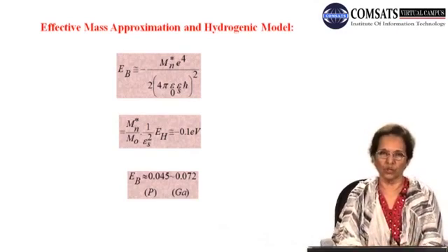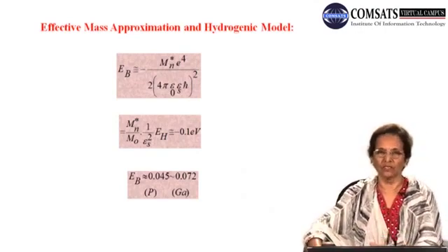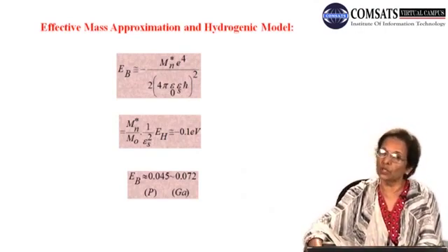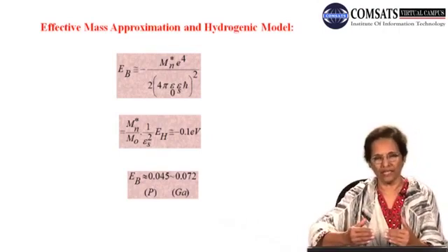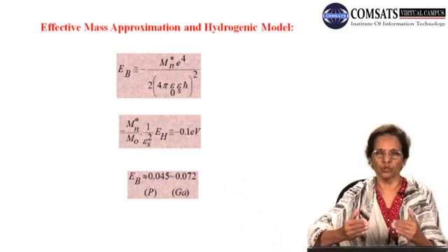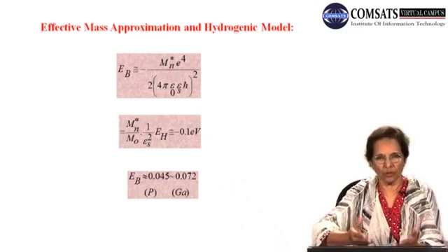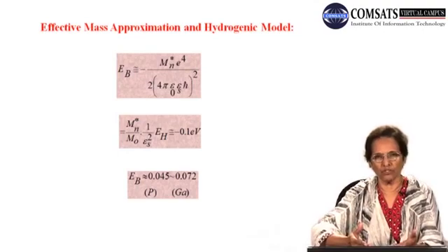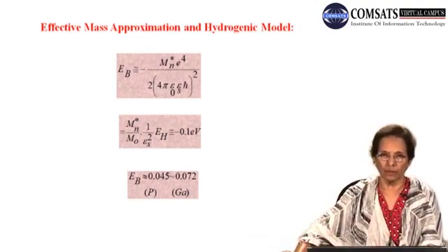That value was 0.025 electron volt. Hence the term we have been using all along, that at room temperature almost all the added impurities or dopant impurities stand ionized. They are already ionized because we require only this small energy, which is easily available to the electrons in the silicon crystal.